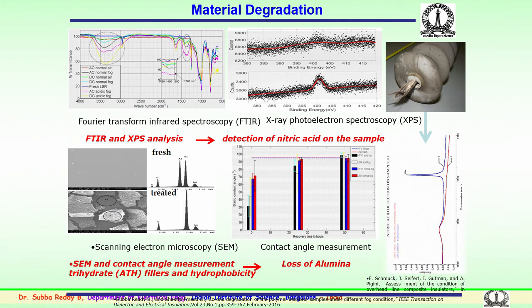So, the material degradation is very important. I was mentioning the surface studies, various morphological studies which are being carried out on the surface after continuously applying the corona moisture or the acidic fog effect. The samples over a period of time after the experimentation are taken out carefully, and these have to be verified. The surface changes, or surface morphological happenings, have to be properly analyzed. For that, as I mentioned earlier, several types of analysis are carried out, like FTIR, Fourier transform infrared spectroscopy, XPS analysis, then SEM, then TGA, and several of these. A few of the information you can see here.